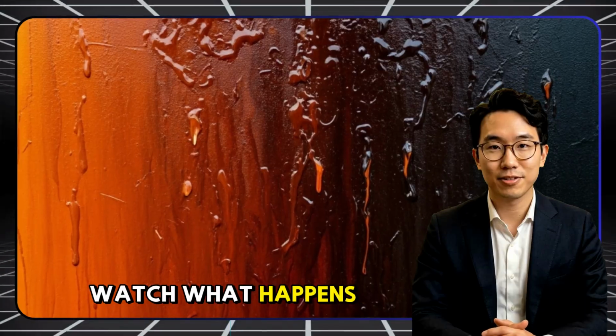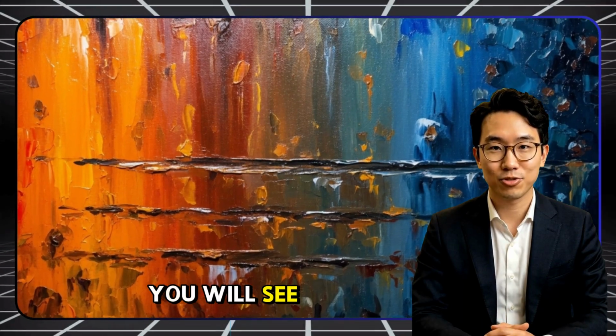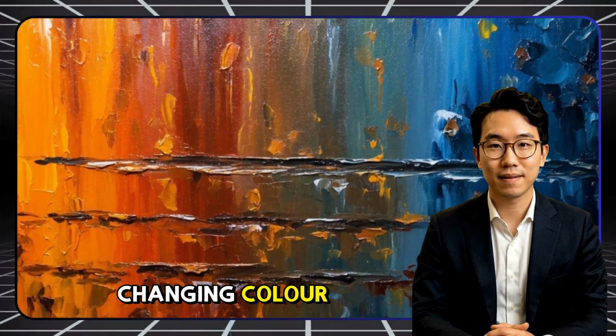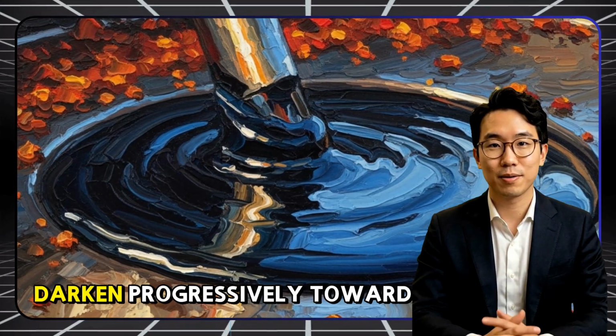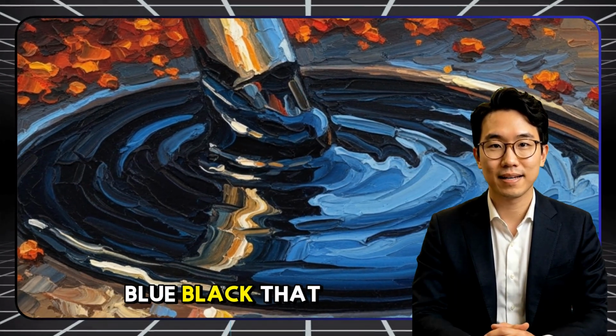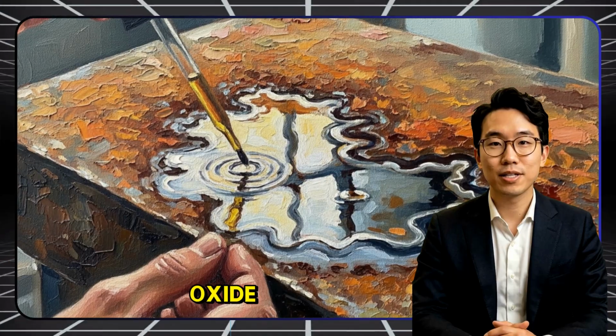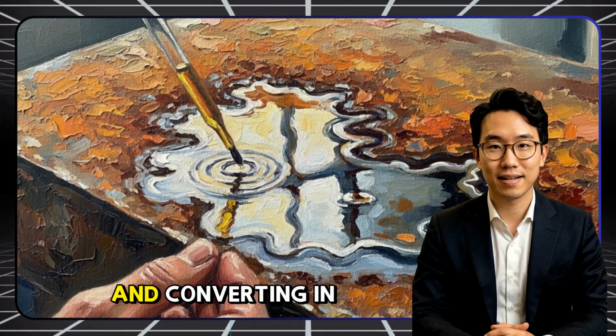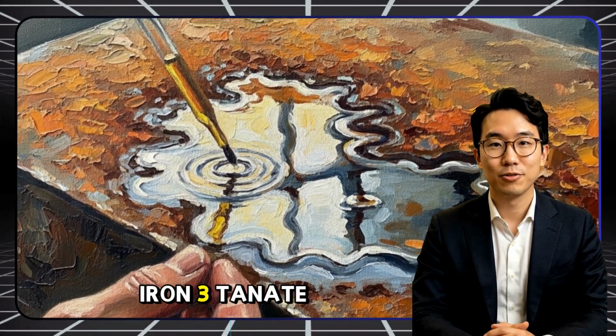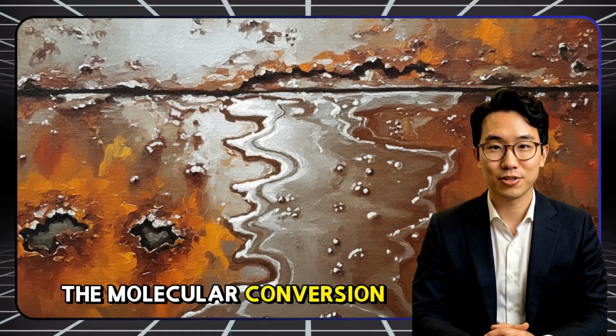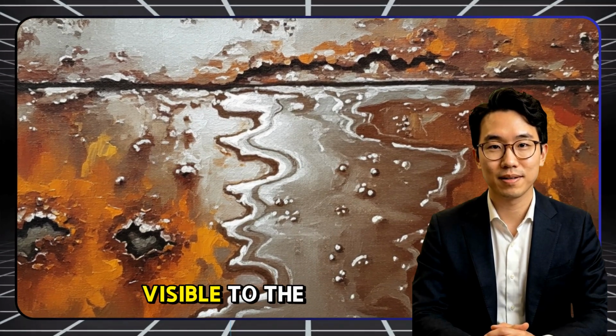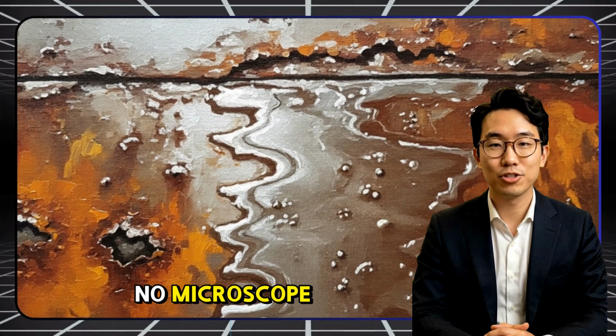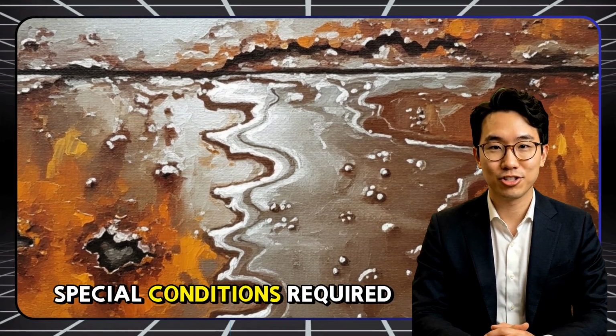Now watch what happens. Within 10 to 15 minutes, you will see the surface begin changing color. The orange-brown rust will darken progressively toward a deep blue-black. That color shift is the iron 3 oxide reacting with the tannic acid and converting in real time into iron 3 tannate. You are watching the molecular conversion happen on the surface of your metal, visible to the naked eye, with no microscope, no laboratory, no special conditions required.